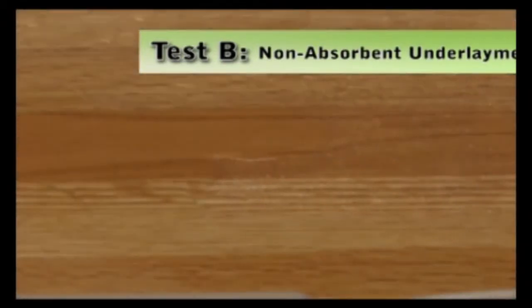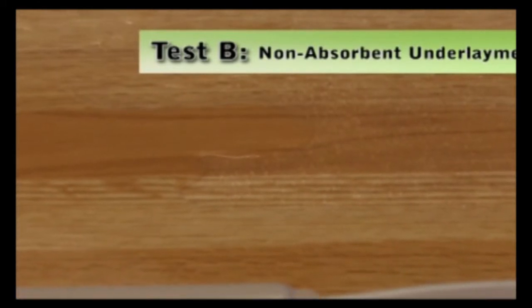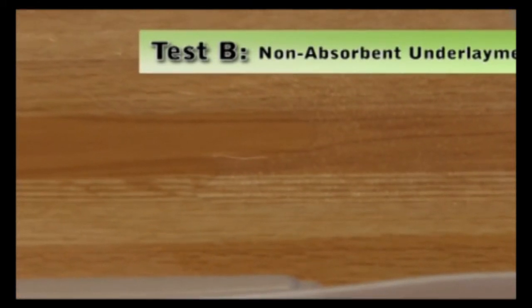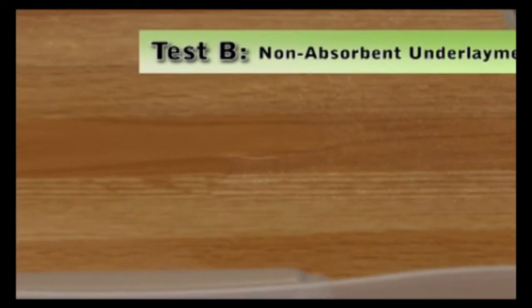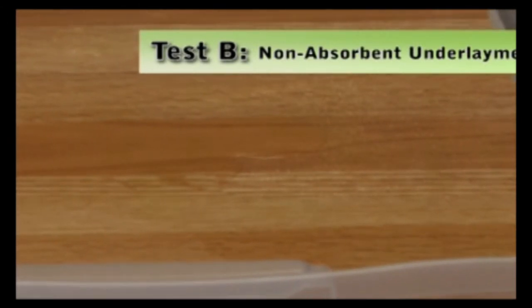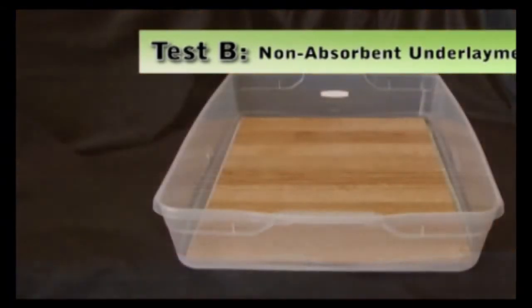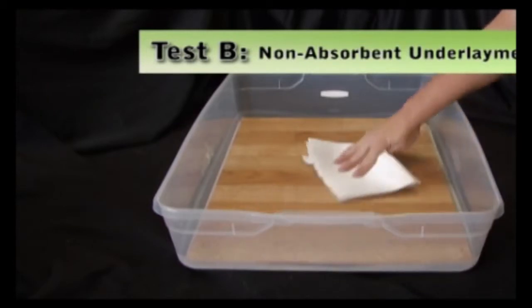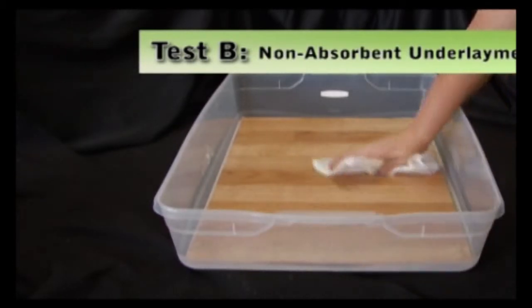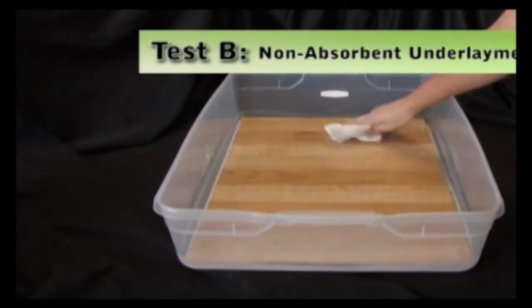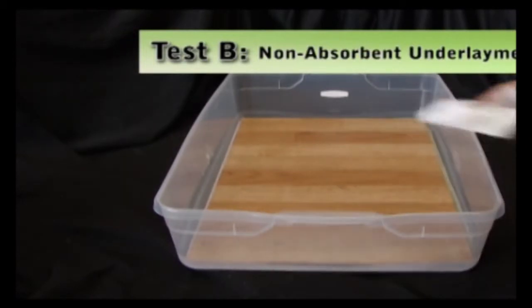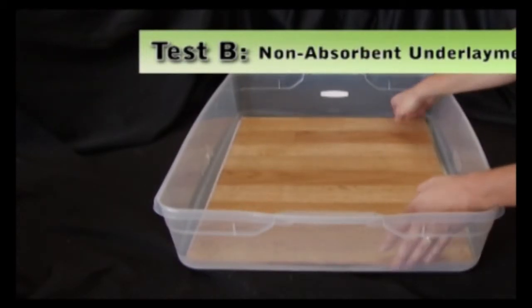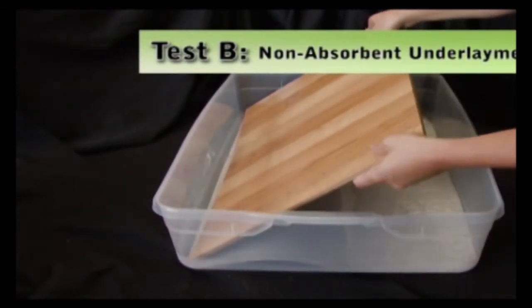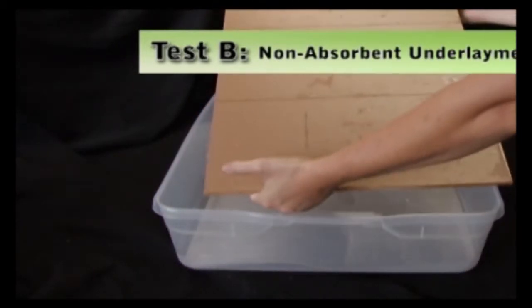The water ran across the surface of the floor and into the perimeter of the test tray. Water seeped both below and above the non-absorbent underlayment. After 30 minutes, the water remaining on the surface of the flooring was dried with a paper towel. The laminate floor was lifted from the side. Water was present on both the underside of the laminate flooring and the top side of the underlayment.